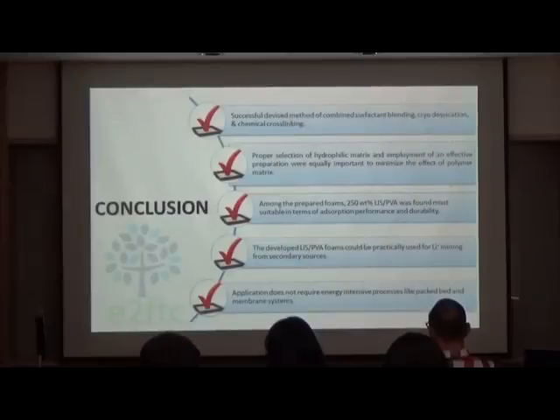First, the successfully devised method of combined surfactant blending, cryo-desiccation, and cross-linking gives us a successful result for the preparation of hydrophilic foams. Proper selection of hydrophilic matrix and employment of an effective preparation were equally important to minimize the effect of the polymer matrix. Among the prepared foams, the 250 weight% composite foam was found most suitable in terms of adsorption performance and durability. The developed composite foams could be practically used for lithium mining from secondary sources. And lastly, the application does not require energy-intensive processes like packed bed and membrane systems, which makes us conclude that this could be better than others reported.